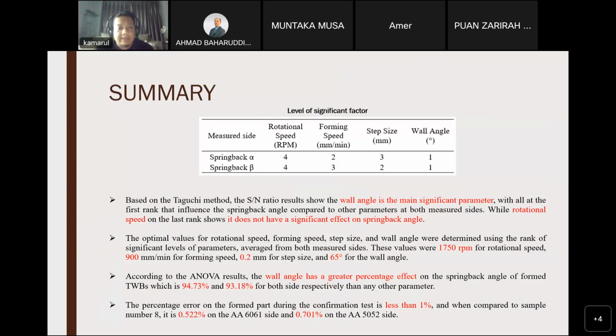On the 5052 side, they have the same significant parameter, which is the wall angle, and also the least significant, which is rotational speed, but the result is quite different between forming speed and step size. The optimal values for rotational speed, forming speed, step size, and wall angle are determined using the rank of significant parameters, like I explained just now.